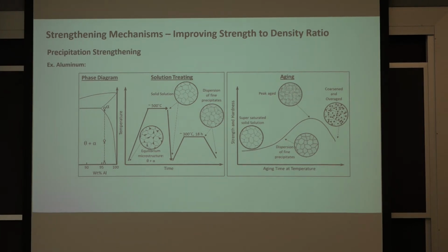That means if you look at the lattice structure of those precipitates, it matches up very closely with the lattice structure of the solvent material. So the atomic planes might line up really close, and they're coherent. They also typically have a higher shear modulus than the material around them, than the solvent, the aluminum.